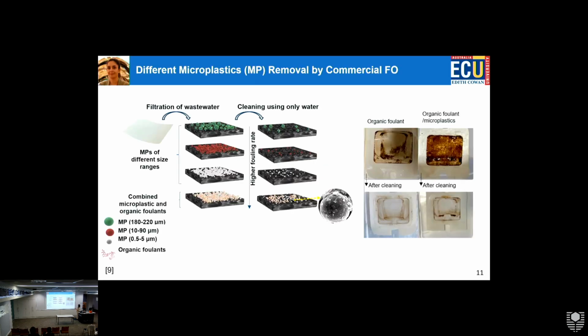So this is the first study that we did on microplastics. This is Mitra, one of my PhD students who has graduated. What she did was she tested different sizes of microplastics. And what she observed was that with the reduced size, we have more fouling on the surface because of the same phenomenon. When the particles are smaller, they have more surface area, they have more active groups, they can attach to the surface more easily. So we had more aggravated fouling in the case of smaller particles.